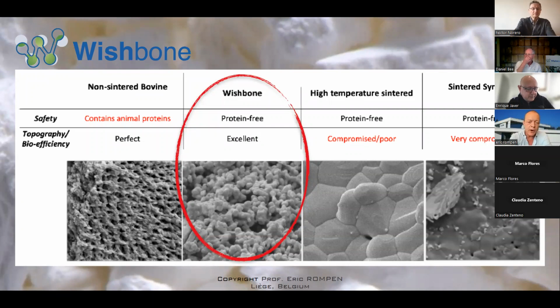So if we summarize a little bit what we have on the market, we have the non-sintered bovine hydroxyapatite, for instance, the BioOss. I think the only non-sintered bovine material available on the market is the BioOss. It's heated only to something like 300 degrees. This material can still contain animal proteins, and that has been published, for instance, by Hassan Nawzari. But the topography is just perfect, excellent, okay? With the Wishbone material, this material is totally protein-free, thanks to the process that I just described, and the topography, the bioefficiency, is also perfect.